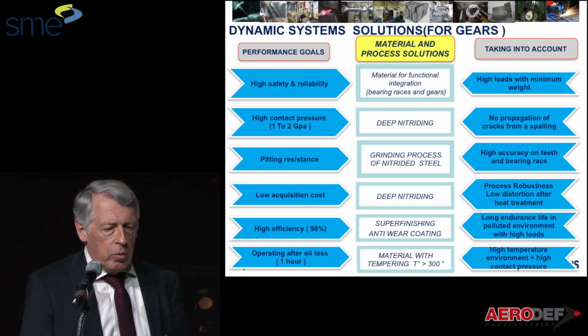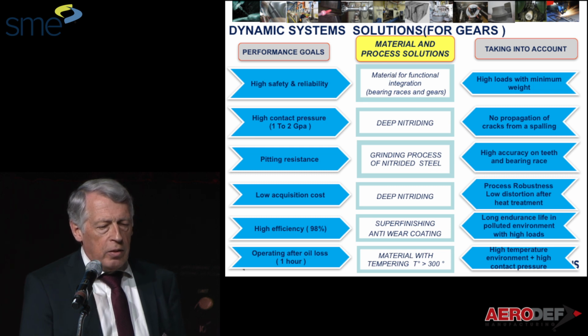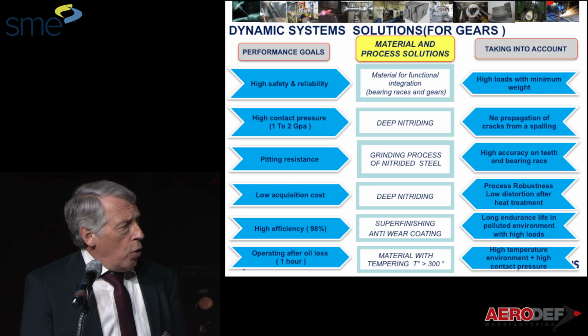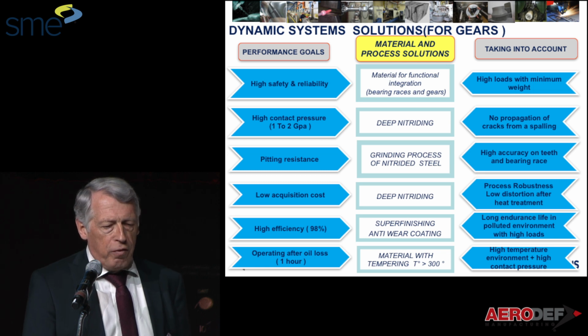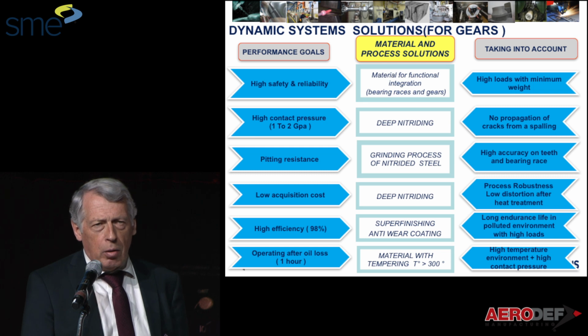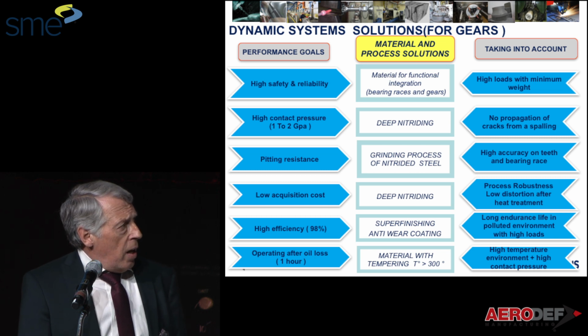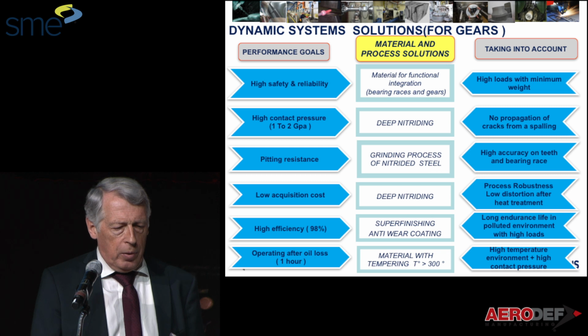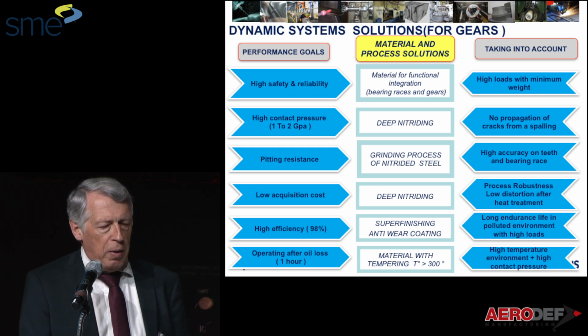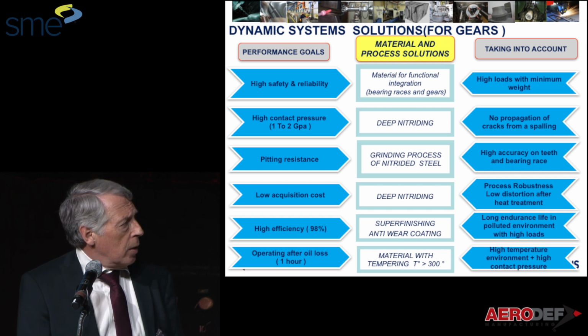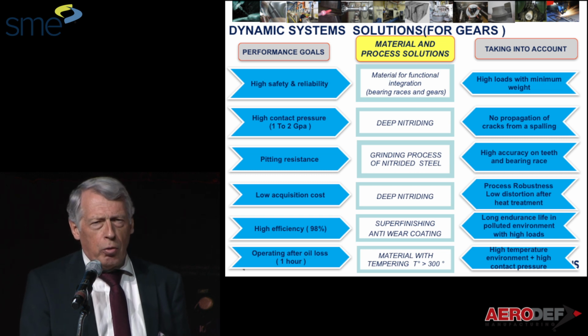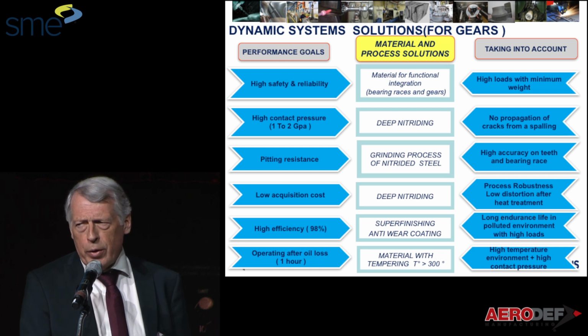Pitting resistance. So here it's a great high accuracy about dimensional on teeth and bearing race. So it's all the process behind that is to master the grinding process on nitrided steel. Low acquisition costs, so here also we have proved that this process, deep nitriding, is cost effective compared to case hardening. High efficiency of the gearbox. So here's all the work we have done on the super finishing and anti wear coating. And operating after oil loss. So the specification for a military aircraft is 1 hour.